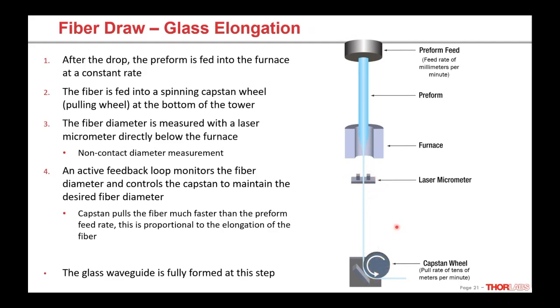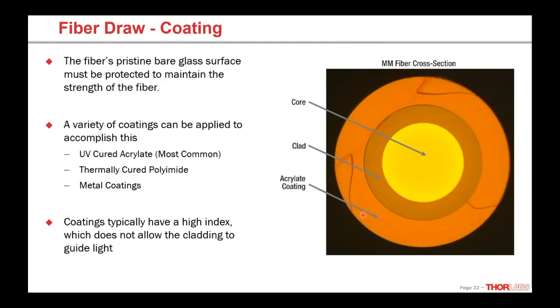At this step the glass waveguide of the fiber is fully formed — we've taken the preform, heated it, elongated it, and we have the fiber design with core and cladding glass. There's one problem though: if you were to draw a bare glass fiber, that outer surface would be exposed to defects from handling or dirt and it would break. So there are more steps to preserve that pristine surface for fiber strength. We add a coating on the fiber — you can see in this microscope cross-section we have core and clad glass, plus an outer coating layer — and whatever the coating type, it seals in that pristine glass surface.